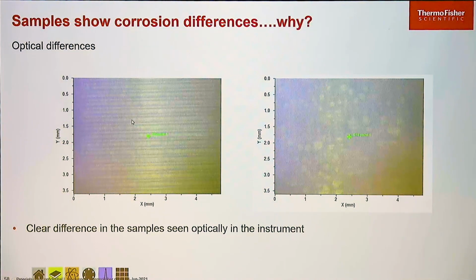But say you have a sample where this layer is a little bit thicker, and so we can't actually do that measurement directly on the surface. So this is a real example of a sample that came into the lab where they'd got two steels that were supposed to be the same, and this one wasn't corroding, and this one was. They were in quite a critical application, so they were going to be under quite a lot of stress, and having corrosion on these parts could cause a significant failure. So they wanted to understand the problem here.